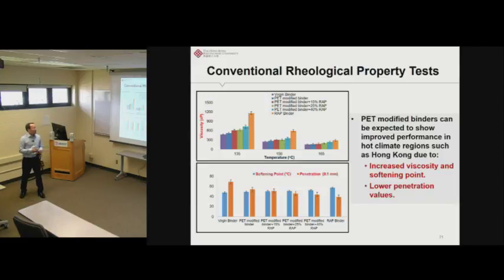So all these test results indicate that the PET modified binders can be expected to show better performance in hot climate regions, such as Hong Kong, where I'm now working. This is because it increases the viscosity of the binder, and also decreases the penetration of the binder material. But notice these tests are conducted at different temperatures. The viscosity increase is actually not that much. So this is important regarding the workability of the binder and the mixture.